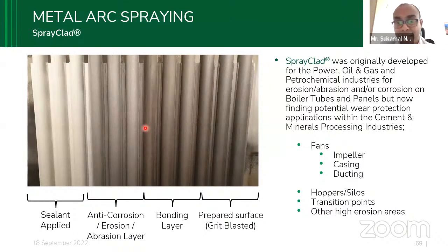Boiler panel cladding is a very good example. You can see here a boiler panel cladding, and this is a sealant applied. This is an anti-corrosion and erosion or abrasive layer, then a bonding layer, and then the prepared surface for grit blasting. So it helps enhance the boiler life.